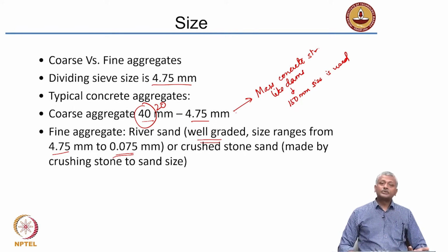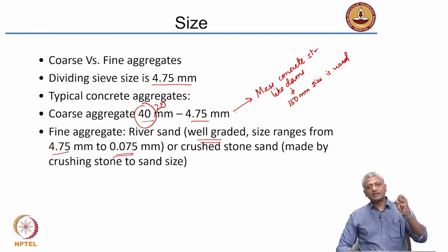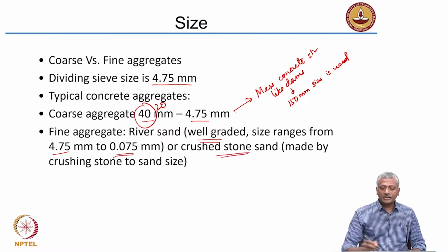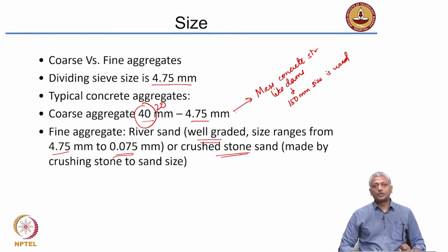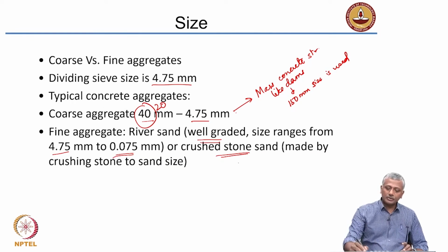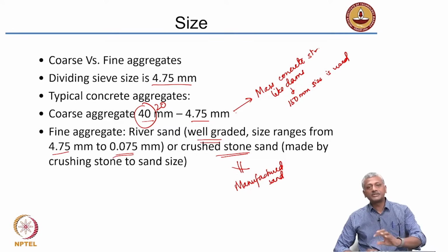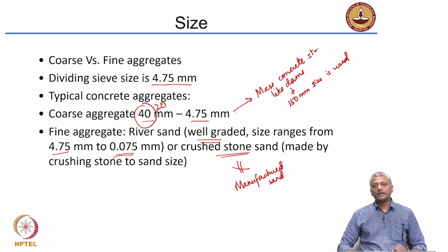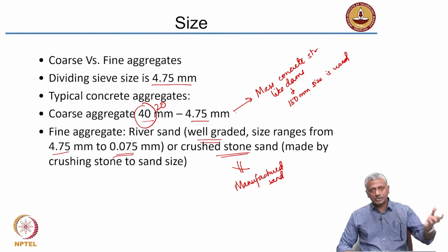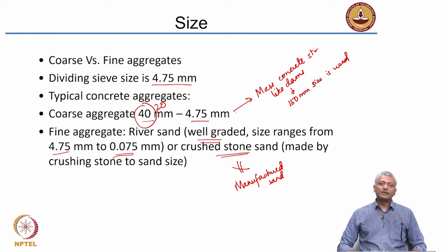Or you can also obtain fine aggregate by taking the stone and crushing it into a smaller size. You get what is called crushed stone sand. It is made by crushing stone to sand size. But please remember, this crushed stone sand is not equal to manufactured sand. Very often people use this interchangeably, but it is not technically correct to say that, because crushed stone sand is still obtained from a natural stone and simply crushed to the right size. Manufactured sand, on the other hand, is obtained from a source that is not natural, I will talk about that in just a minute, and then processed to aggregate size. So, that is a little bit different, manufactured sand as opposed to crushed stone sand.